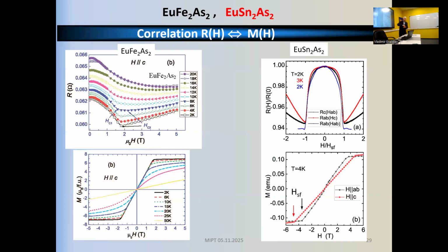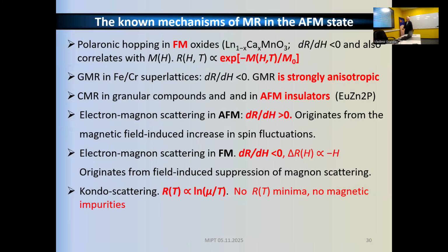When you rotate the magnetic field in plane, nothing changes, but when you turn it perpendicular to the plane, it's a little bit harder to magnetize, and there's a minor difference. But when you scale this data for magnetic resistance on the saturation field, which is a complete spin polarization field, then it exactly matches each other. So it's an isotropic effect. The magnetic resistance is isotropic.